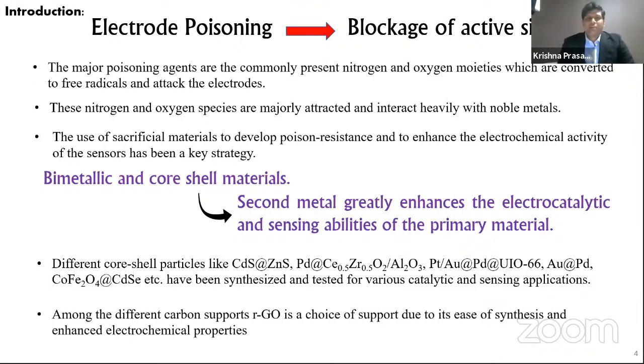So here we have come up with a strategy wherein we use noble metals as sacrificial materials to develop poison resistance, and they could in turn enhance the electrochemical activity of the sensors. And bimetallic core shell based materials have garnered significant interest, as it has been understood that the introduction of a secondary metal greatly enhances the electrocatalytic activity and sensing abilities of the primary material. This is because of the adsorbed intermediates leading to in-structure induced promotional effects.